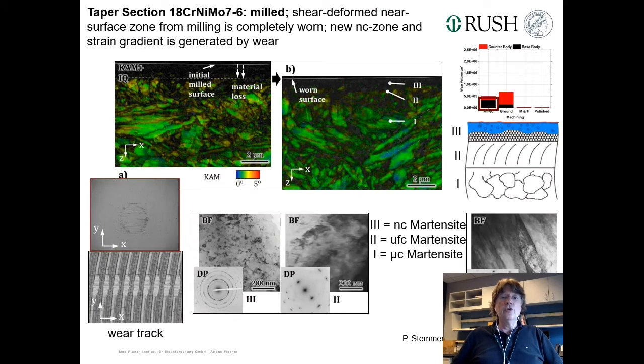So then when you do EBSD, you could see the martensite. It's a bit tricky with EBSD, but Priska Stemmer was able to do this. And you see the wear scar on the milled surface, and here the wear scar on the counterbody. This was the incipient surface after the fabrication process, and that has been worn down here in that wear test.